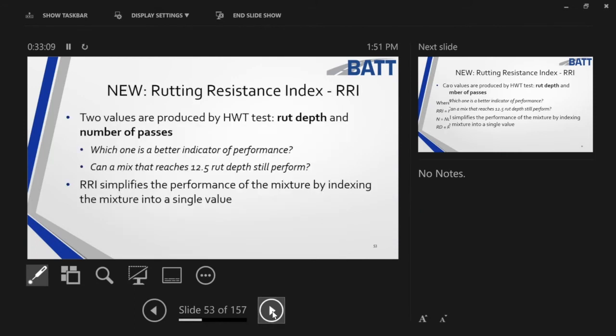Okay. A new way to look at this is there's a thing called an RRI. And one thing that I like with the RRI is I'm able to take a value. Let's say I run everything out to 20,000 passes and one of them has 10 millimeters of rutting and the other one has 4 millimeters of rutting. Normally, I would say they both performed. Well, I need to be able to rank those. So RRI allows us to simplify this performance.